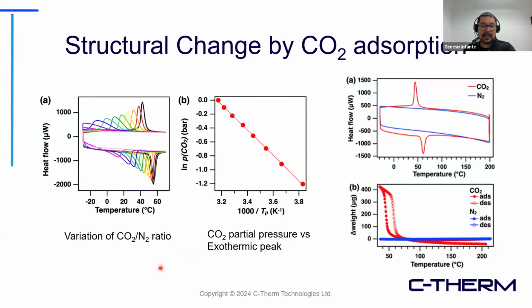Another example right here is essentially a DSC with some TGA, but this is effectively a DSC signal. You can see there's a bunch of different spectra in there, with different coloration. If you follow the colors from purple all the way to black, that is where they vary the CO2 to nitrogen ratio. Coming from the purple, it's mostly nitrogen, not a lot of CO2, and as you go along it's just CO2. You can see here that the MOF itself is behaving differently, meaning your thermal events are shifting as you change the amount of CO2 available for exposure.